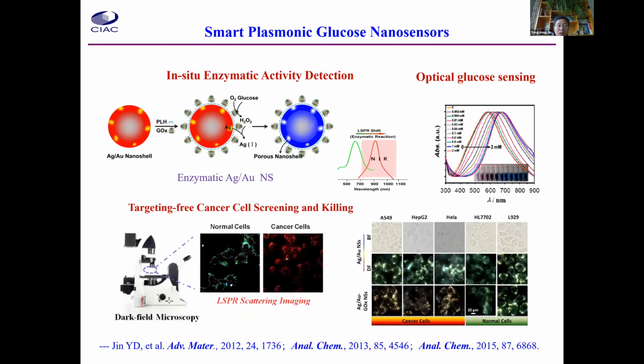Our group also prepared smart plasmonic glucose nanoprobe. Recently, we prepared enzymatic gold silver nanoshell by depositing glucose oxidase on the surface of silver gold bimetal nanoshells. The enzymatic reaction will result in the dissolution of silver from the shell, resulting in a nanoporous nanoshell. In the process, a significant LSPR shift occurs, so it can be used for sensitive optical glucose sensing and also in situ enzymatic activity detection. Since cancer cells usually have higher glucose uptake levels than normal cells, the sensor has been exploited for targeting-free cancer cell screening and selective cancer cell killing.